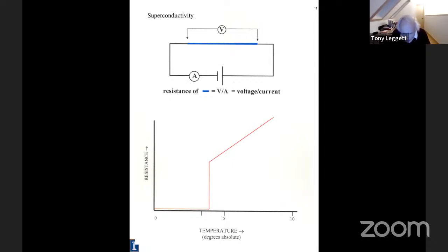Then I ask these kids to imagine what will happen if the current does not die away, but keeps on flowing forever. Some of them guess correctly that the magnet will just stay suspended. Then I show them a pellet of high temperature superconductor, say yttrium barium copper oxide. I cool the pellet in liquid nitrogen, then take the magnet and try to lower it. Sure enough, it doesn't fall. It stays suspended in the air above the pellet. That is the phenomenon which you know as superconductivity.